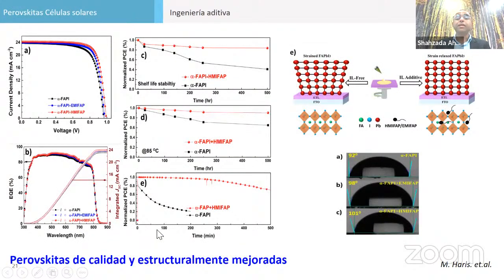We also put in additive engineering, meaning ionic liquids, which are very hydrophobic, or fluorinated molecules. So we put some highly fluorinated molecules in it. We can see the ordering of the crystal is almost perfect here. This also pushes our performance. And we have measured very good stability by using this additive engineering. Why did it happen? If you look at the surface properties, the contact angle measured is 92 degrees, and it improves to 100 degrees. I mean, the surface became more water repelling. It means environmental moisture cannot attack it. So the red part you can see is the stability here.